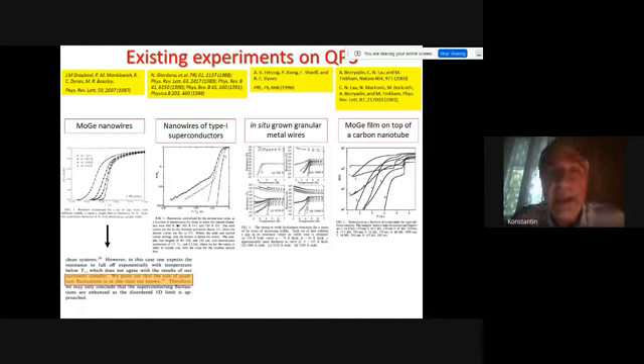A couple of years later, again in the group of Dynes, they observed very strange superconducting transitions which were not tending to zero resistance even at lowest temperatures, but they did not attribute this effect to quantum fluctuations. And the big punch to this topic was made in the group of famous Professor Tinkham, where his PhD student Alexei Bezryadin used a very elegant technique. They used a non-conducting carbon nanotube, suspended it and used it as a substrate, and then covered it with molybdenum germanium, which is a superconductor, and they observed the strange dependencies shown here, that not all of them were extrapolating to zero temperature resistance.